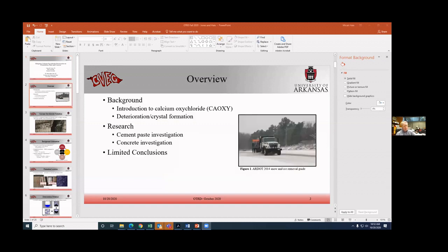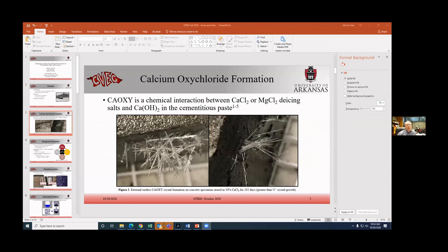So a little bit of the background, make sure I don't go over. So we're going to go over kind of what calcium oxychloride is, some of Casey's research, and some of our limited conclusions. So calcium oxychloride is a chemical interaction between either de-icing salts, which can be calcium chloride or magnesium chlorides, and then the calcium hydroxide that's in the cementitious paste. So we all remember back to our cement chemistry, where the main strength component to harden concrete is the calcium silicate hydrate. Then you also have the calcium hydroxide. So what happens is the de-icing salts, whether they're calcium chlorides or magnesium chlorides, they interact with the calcium hydroxide to form this calcium oxychloride.